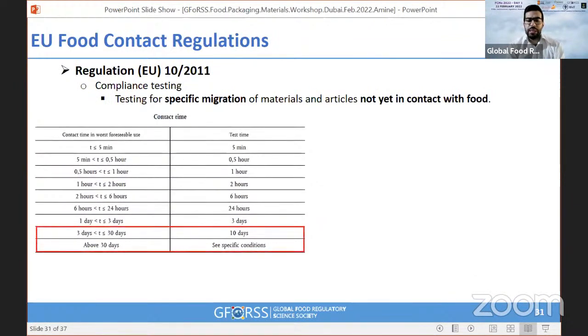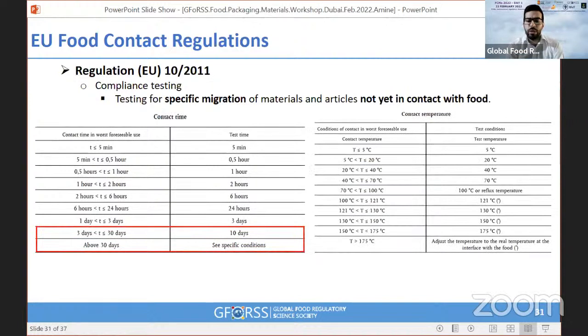Also, the regulation, as I mentioned, states the actual test conditions, similarly to the FDA framework, to be applied. Let's say the actual use is between 3 days and 30 days. We have to apply 10 days for the test. The actual temperature used is between 20 degrees and 40 degrees, let's say room temperature conditions. We have to apply 40 degrees for our migration tests in order to simulate the worst case scenario.